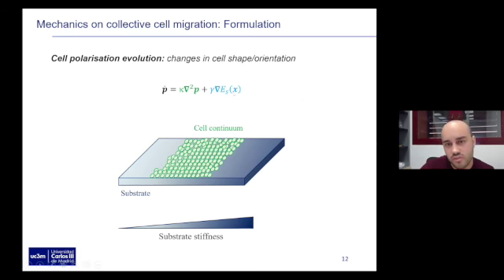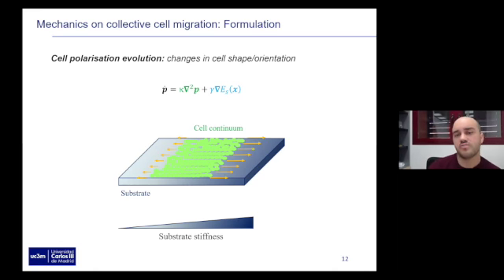So first, this blue term is saying that because of this stiffness gradient, we can have some cells that are going to polarize to a stiffer region, right? Then we have this first term saying that as all these cells are linked and attached to each other, we're going to have a diffusion-like process where all these other cells are going to lead to that polarization. So even if we keep a constant propulsion force, what we're going to have is a resultant force towards this stiffer region that is going to be able to capture this tendency in the migration dynamics.